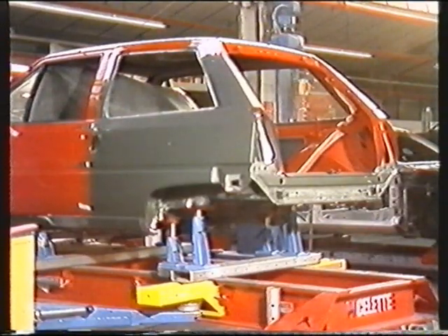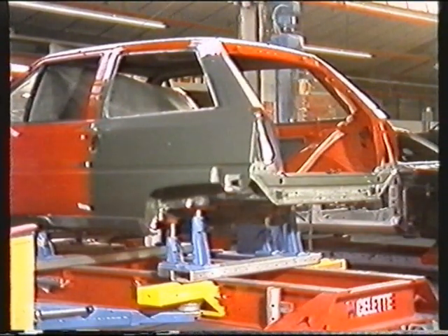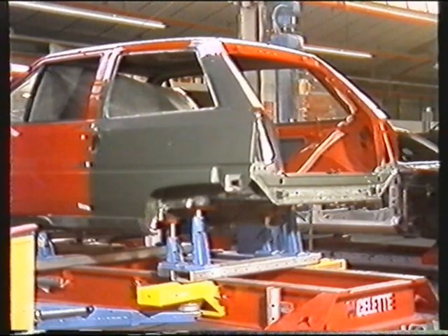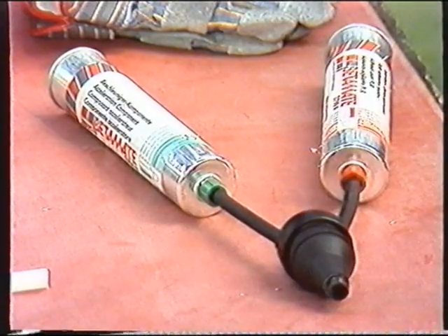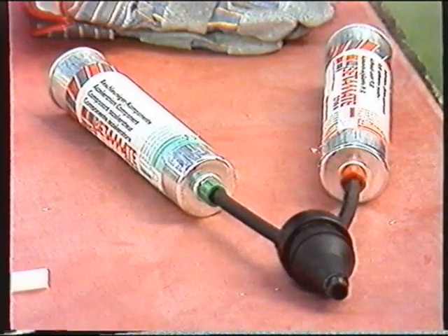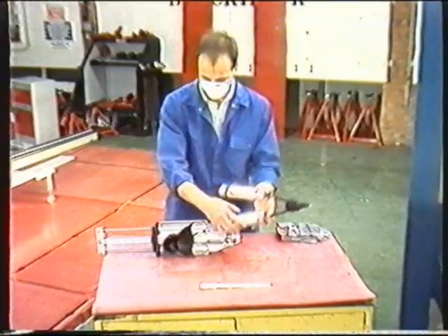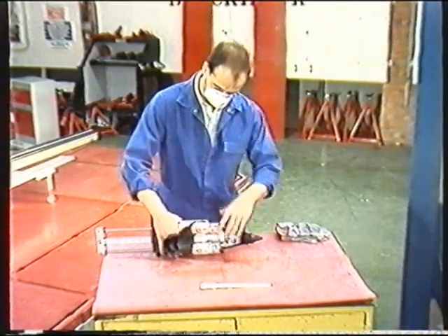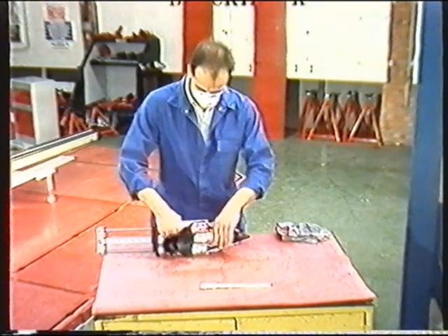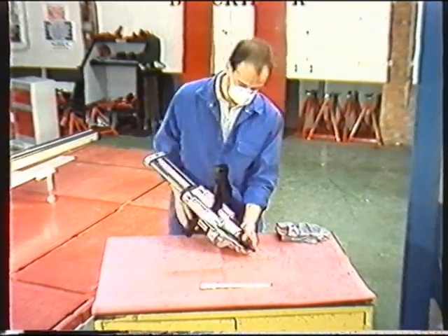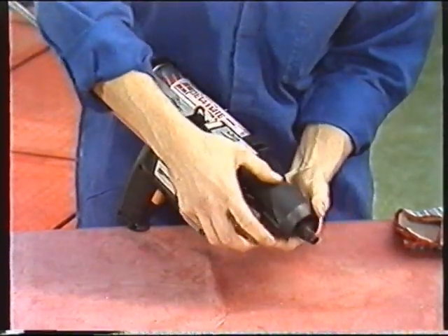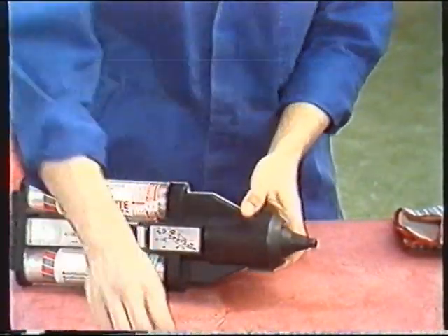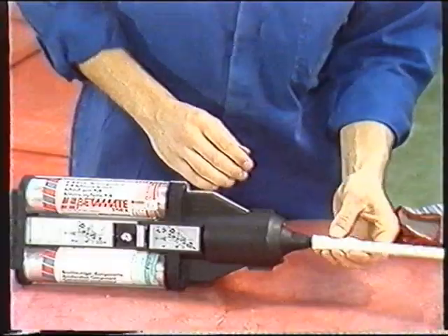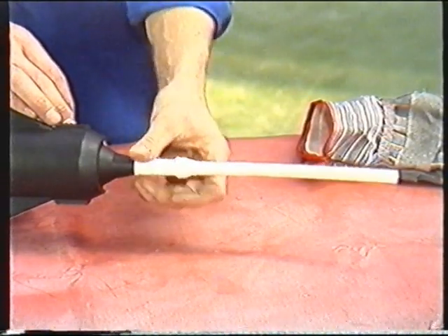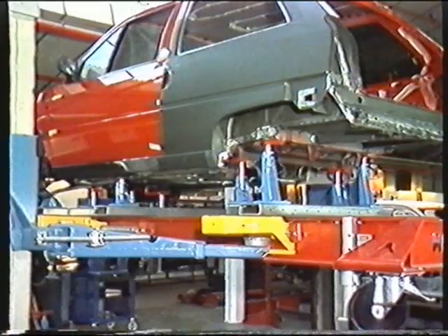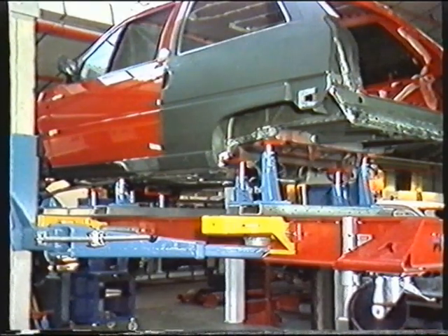The car was repaired, and a decision taken to replace the original material with a 2-component polyurethane-based adhesive sealant. This was chosen particularly because it cures by chemical reaction and not by moisture, as in the case of single-part polyurethanes. The risk of corrosion is thus significantly reduced. A special nozzle had to be made up for the gun to overcome the difficulty of access underneath the wheel arch.